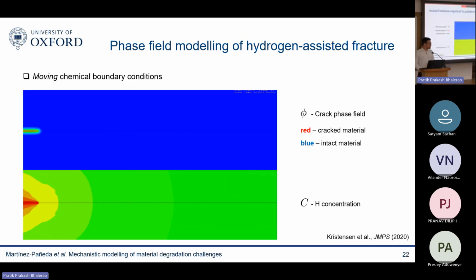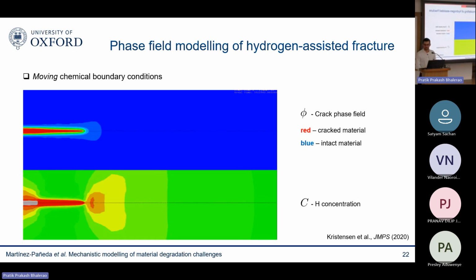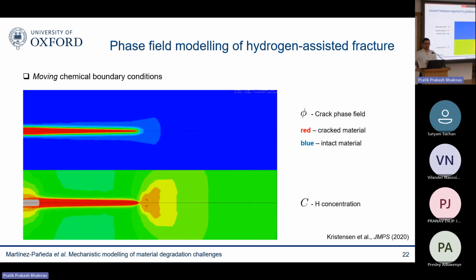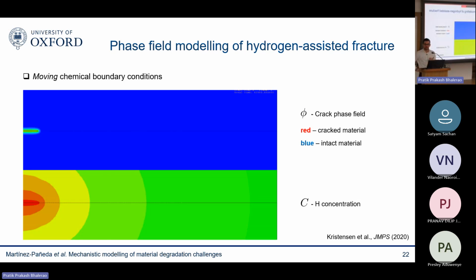Before I do so, let me show you another aspect that I haven't mentioned before, which is another aspect of the coupling. Now, we're not only interested in the initiation of cracks. For that, you probably can handle well with the stress intensity factor approach. We're interested in the propagation of cracks. And when you look at the propagation of cracks, then what you need to make sure is that you capture how the hydrogen environment follows the crack.